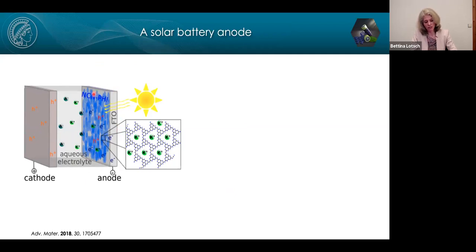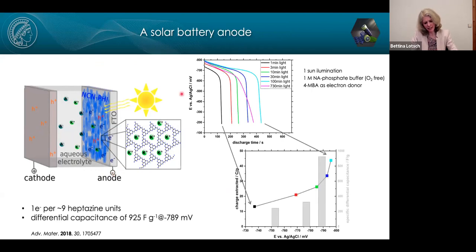So what we've done is we've deposited PHI on a transparent substrate, FTO, and by irradiating it for increasing periods of time, you can see here that the photopotential increases, and we can discharge the system and regain increasing amounts of charge. Increasing amount of illumination then translates into increasing amounts of charge. The charge density is not super high in these systems, so it translates basically to 1 electron per 9 heptazine units in a very unoptimized system. But we believe that the capacitance can clearly be much more enhanced.